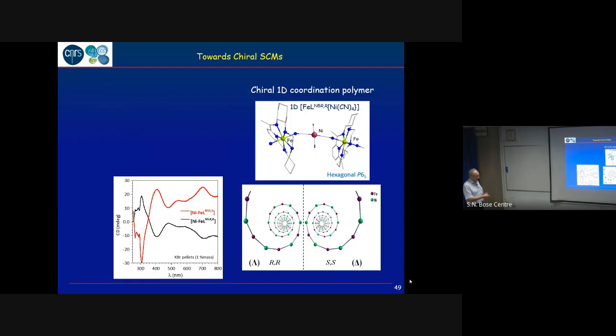So let's say you do the synthesis in solution, and after that all characterizations are done. These are stable at room temperature and air stable. Yes, this one is air stable. So this is a crystal structure, and this has been recorded in air. Of course, it depends on the stability. Sometimes you have to work under nitrogen because, for instance, iron is sensitive to oxidation. So we keep it under nitrogen, but with nickel we don't have any problem. So here with iron, this was done under nitrogen to avoid oxidation.